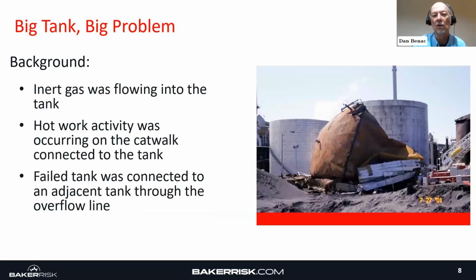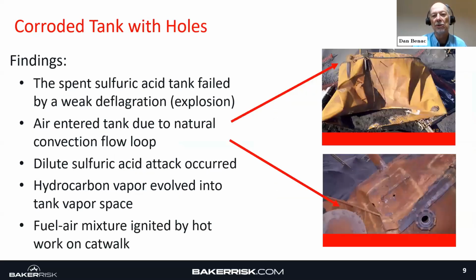So there was hot work activity going on above this particular tank. And the failed tank was connected to another tank. That's important because there was natural flow that had occurred to allow air to go into this particular sulfuric acid tank, unbeknown to the hot workers at the time. As they were doing work, unfortunately, a very tragic fatal situation occurred where an explosion, what we would call a deflagration, occurred inside the tank, rattled the tank, and literally lifted this tank off its base into the air and threw it on its side.